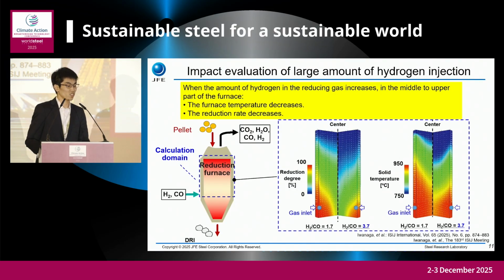And this slide shows the effect of increasing the hydrogen ratio in the reducing gas on the distribution of the reduction degree in the shaft furnace. This is an example of numerical simulation of the reaction behavior in the furnace. The composition of the reducing gas is assumed to have a hydrogen to carbon monoxide ratio of 1.7 and 3.7. The center figures show the calculated distribution of reduction degrees.